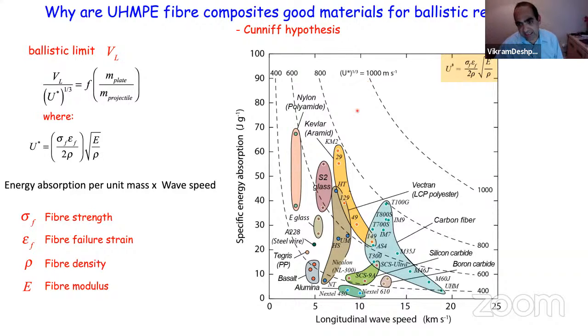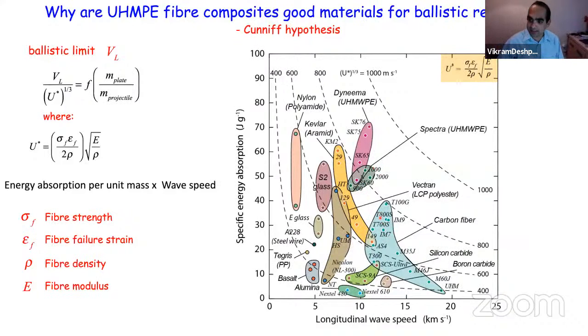So what is that telling you is that, of course, you want to be as high up as possible in u star. And Kevlar is somewhere here, carbon fibers are somewhere here. These ultra-high molecular weight polyethylene composites are here. And of course, you can see they're doing better than Kevlar and carbon, and that is why people consider them.